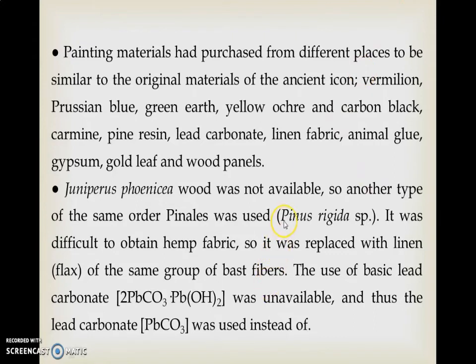We designed the models with almost all of the original materials, such as vermilion, Prussian blue, green earth, yellow ochre, carbon black, carmine, pine resin, lead carbonate, with small differences, such as we used Pinus rigida instead of Juniperus phoenicea. We used lead carbonate instead of basic lead carbonate, and the hemp fabric is replaced with linen flax of the same group.